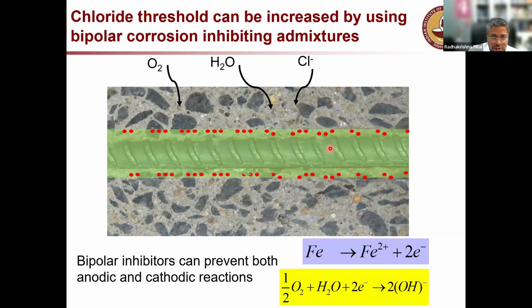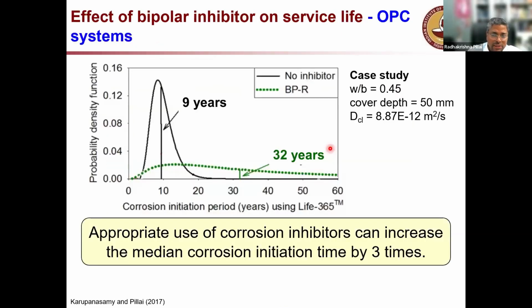Now, how do we put this corrosion inhibitor? It is a chemical which is available. You can buy it in the market, and then you mix that with the concrete and then use the concrete. That's how we do it. Now, this is a study which we have done where we have clearly found that the use of inhibitors can enhance the chloride threshold, and eventually the effect of that is increasing the service life by 3 times. This study showed 3 times, let's say at least 2 times.